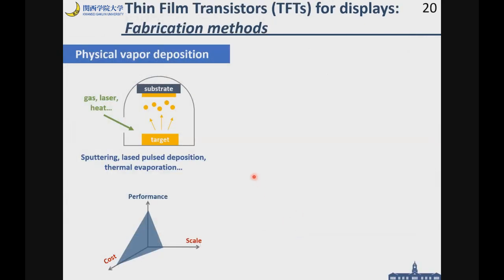fabrication method. So far, thin film transistors have been fabricated by physical vapor deposition, such as sputtering, laser pulse deposition, and thermal evaporation. In this case, we use a vacuum. So the target material, which will form the thin films, and the substrate are put into the vacuum chamber and evacuated by a vacuum system. In this case, the fabricated thin film shows a high quality, and the devices fabricated by this method show high performance, but it is very costly, and we cannot fabricate large scale devices because we need to put all of the materials into the vacuum chambers.